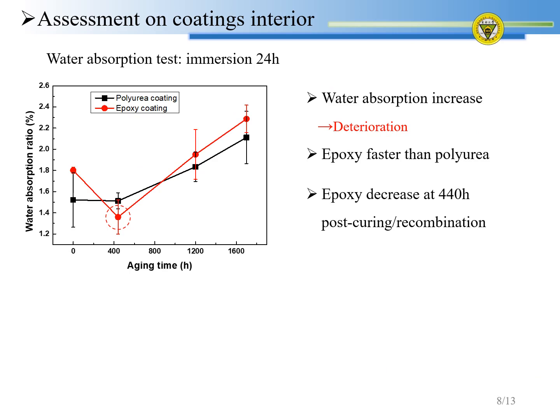Next is the internal structure. In the water absorption test, both epoxy and polyurea coatings show the same upward trend, indicating that the number of pores or free volume is increasing and water can pass through these pores. The same as before, polyurea is more stable than epoxy resin. But there is a decline at 440 hours for epoxy resin. This is related to the post-curing of epoxy, resulting in a denser structure.